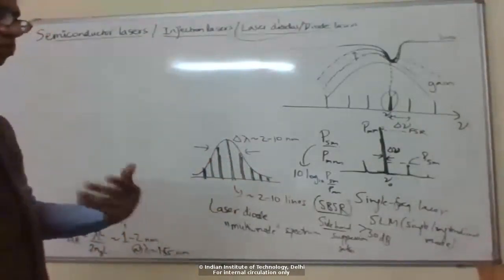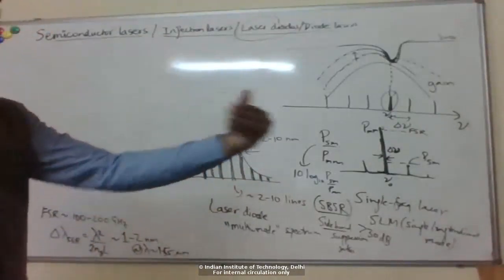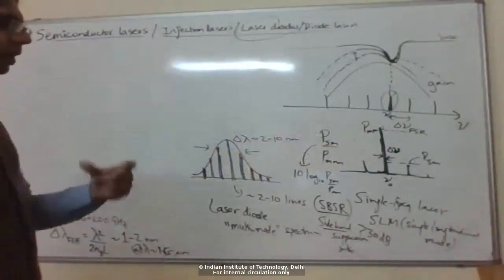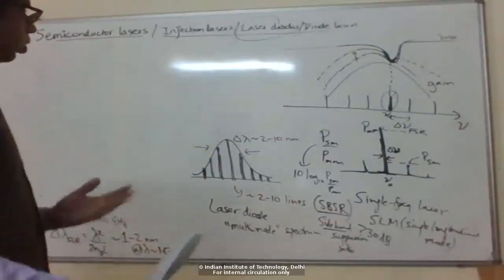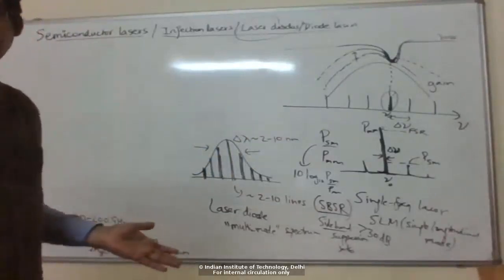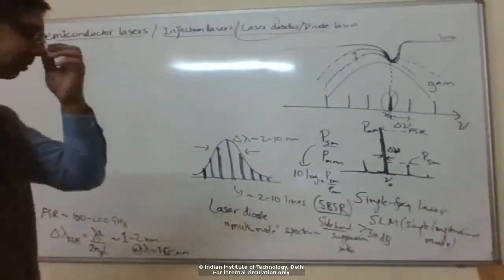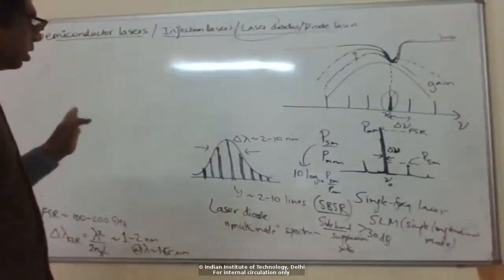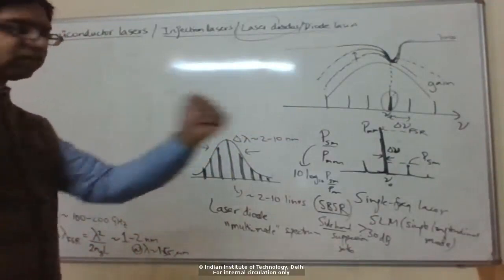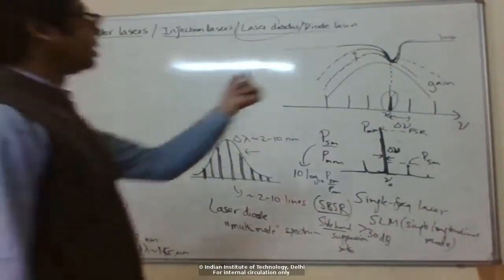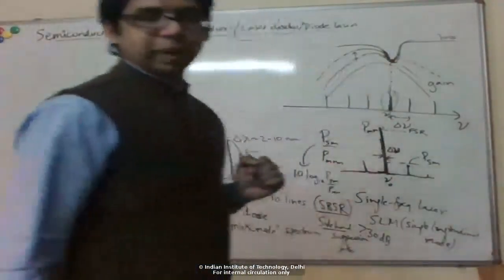For example, a popular way to make mirrors is multi-layer coatings. Depending on the period of these coatings, that decides the wavelengths which are reflected. And you know about the concept of Bragg reflection already. For example, in fiber Bragg gratings, you vary the refractive index periodically, and that reflects a particular wavelength, or a very narrow bandwidth around a particular wavelength.